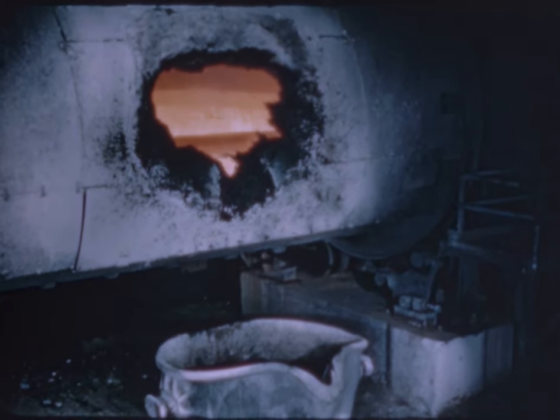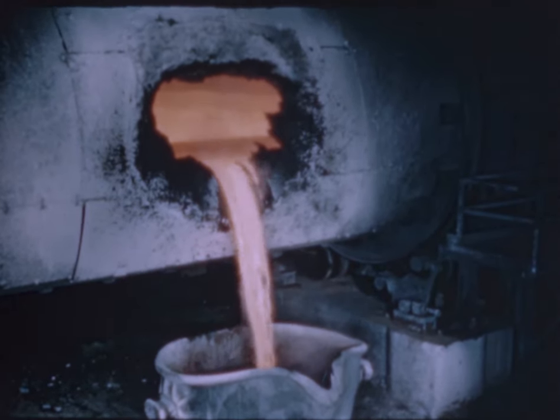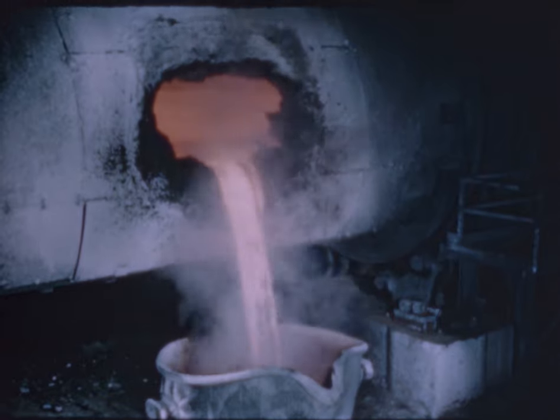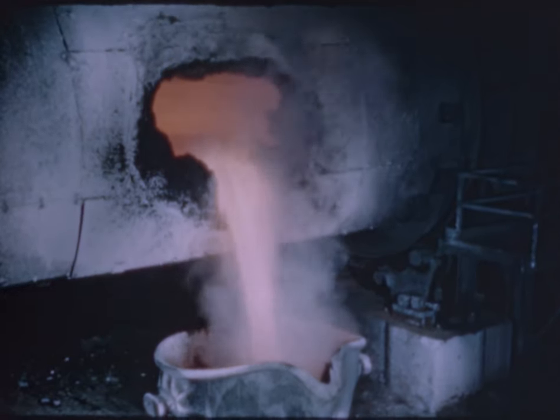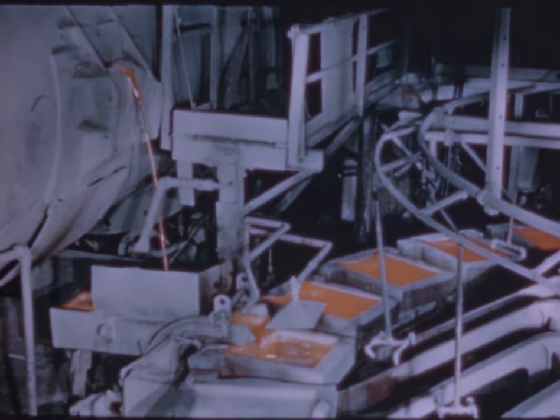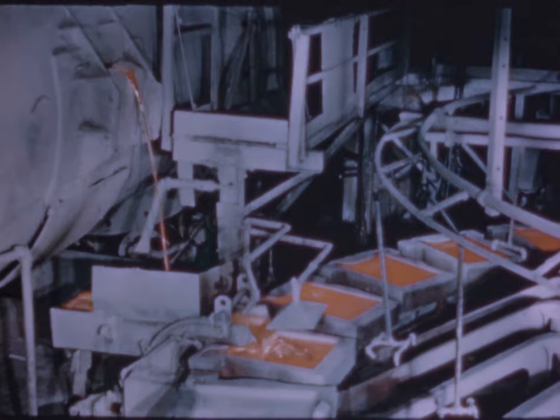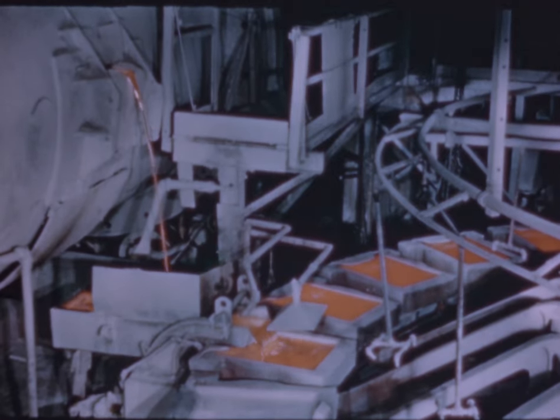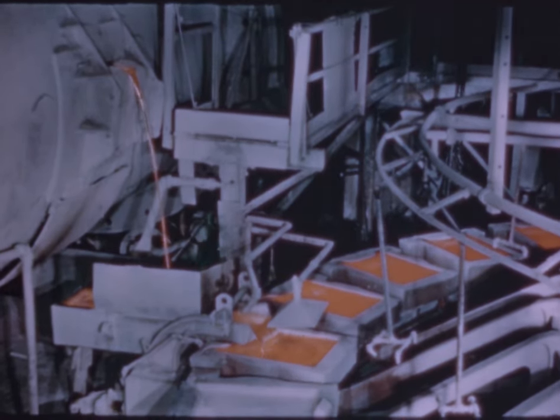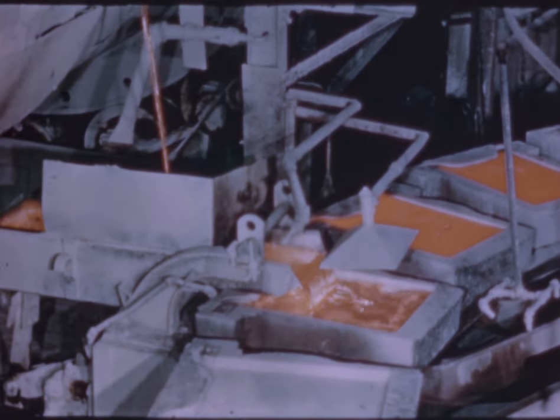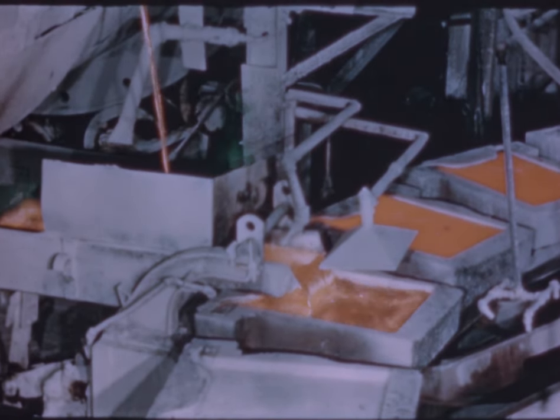The product resulting from the final converter operation is blister copper, approximately 99% pure, but not yet pure enough to be used commercially. Most of the remaining impurities are removed by a further blowing operation here in the casting room. The copper is now ready for casting 425-pound anodes, which will be used for the production of electrolytic copper.